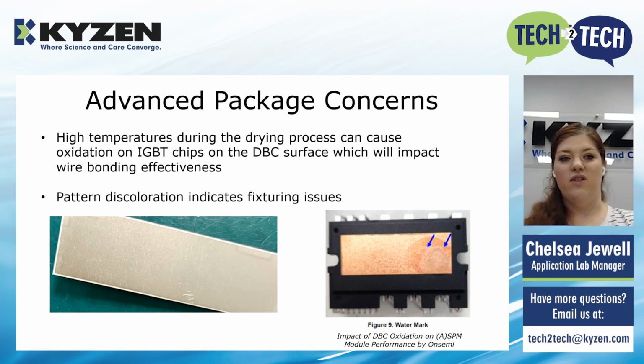Another indicator that drying isn't efficient is fixturing marks. On our nickel DBC, we're seeing little rectangles that are showing patterns after the drying process. What we're seeing here is there's moisture trapped between the fixture and the surface of the board that's causing this pattern discoloration. So, going back to those air knives, how is it moving water off? Are you pooling moisture there in between that fixture and the DBC, creating that oxidation type environment, or is it free flowing and able to be blown directly out of it? Those are some considerations that we would look into if you were seeing drying marks or pattern oxidation type materials on these type of assemblies.